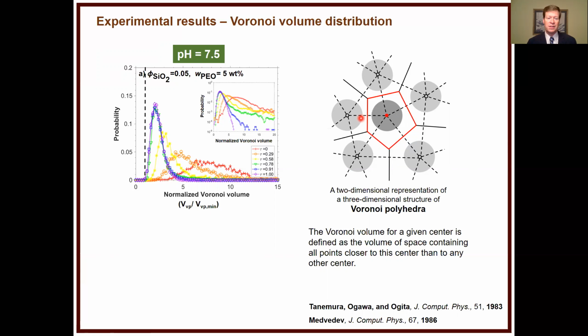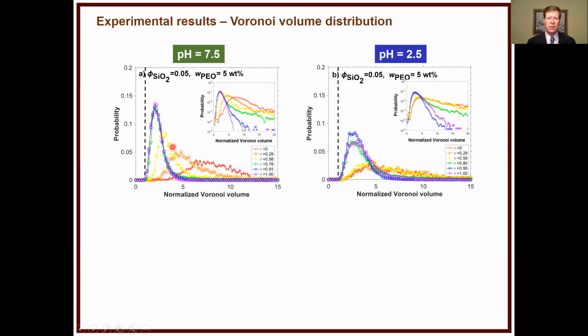Now, of course, we are looking at disordered systems, so the dotted line is that minimum volume that I just described. And now we're going to always look at distributions of volumes that are much larger. You can see many of these are as much as 10, 15, 20 times as large as the standard one. What I'm showing you on the left-hand side now is a probability distribution of all the different types of these free volume spaces taken up by particles. You can see it starts relatively broad, and then as it dries, gets narrower and narrower, and eventually compacts down to the point where essentially there's no change in microstructure anymore. And so that was for pH 7.5.